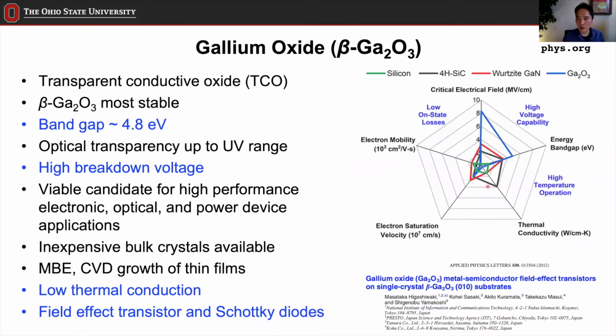This particular plot here is comparing gallium oxide with other wide bandgap materials such as silicon carbide or gallium nitride. You can see some of the properties are way better. As I said, the critical electric field, which is related to the high breakdown voltage, is way higher than other materials. And the band gap is also high. But there are other drawbacks too. The electron mobility is actually smaller than others, and thermal conductivity is also small. But these drawbacks are something that we can handle.